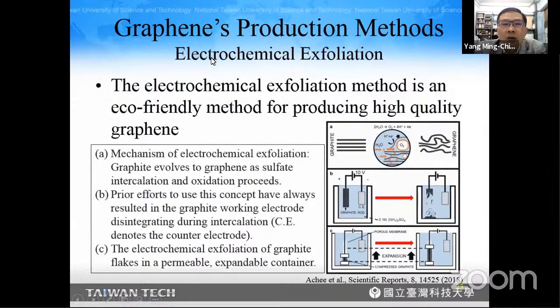And this is a new one, electrochemical exfoliation. The electrochemical exfoliation method is an eco-friendly method for producing high quality graphene. This figure shows the basic method. Here we have a graphite after treating in an electrochemical process, and oxygen is produced due to the dissociation of water, and oxygen is produced between the layers, which will expand this graphite layer into single monolayers. And this is a traditional electrochemical method.